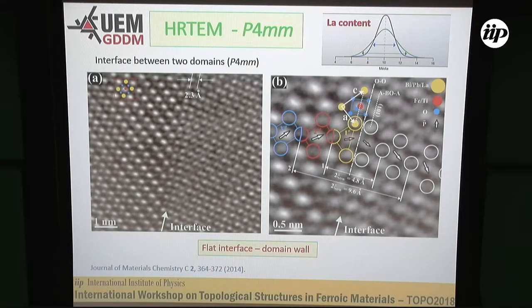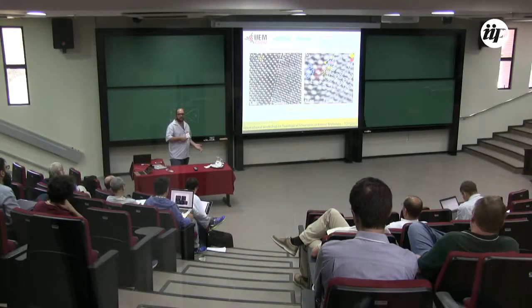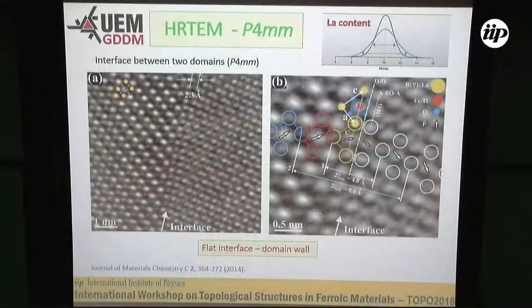If the second unit cell is also distorted for the very huge strain field in this region, your interface is still bigger, 9.6 angstrom, about 1 nanometer. And you see this depends on the way that you prepare your sample. If you do quenching, if you put some strain, you can change the width of this interface, for example if you have here a strain field in this region, or some electrostatic screening or whatever else. You can tune this width by changing your sample preparation conditions, or, in our case, by doping with lanthanum or controlling the concentration of lanthanum in our sample. You can change this.